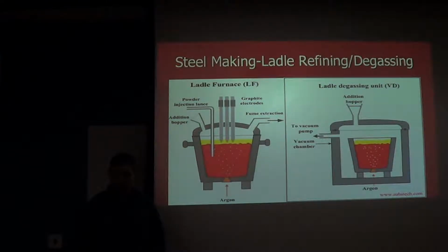About 3,000 degrees, yeah. Your refractories are usually only good to about 3,200, 3,400? I'm not sure what the upper limits are. I think it's like 3,400 if it's magnesia or something like that. Yeah. And so you're right at the edge of what the refractory can do itself. And the refractories break down and have to be replaced or repaired. That's a normal part of the steel making process. These things have to be refurbished on a regular basis.